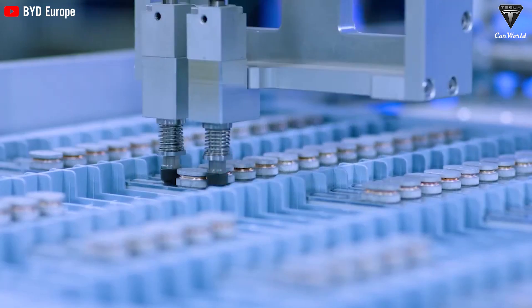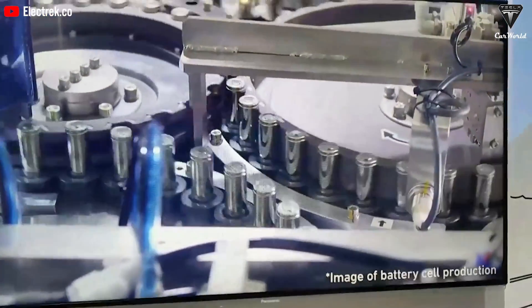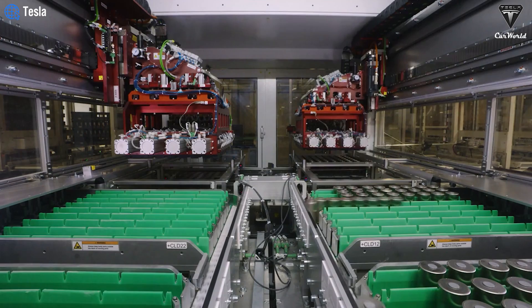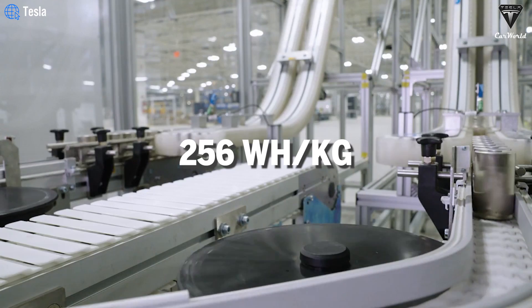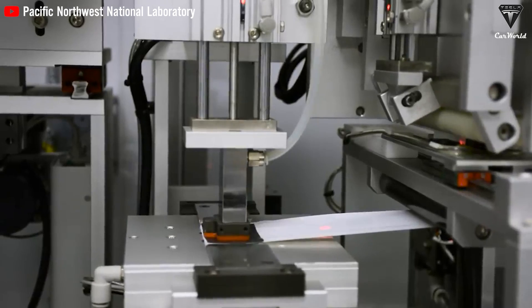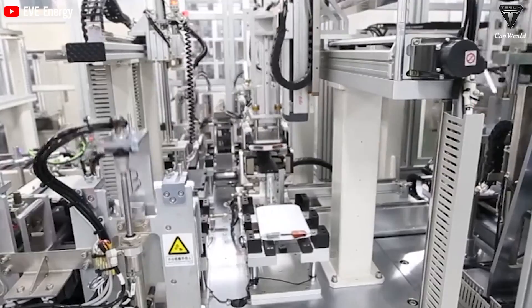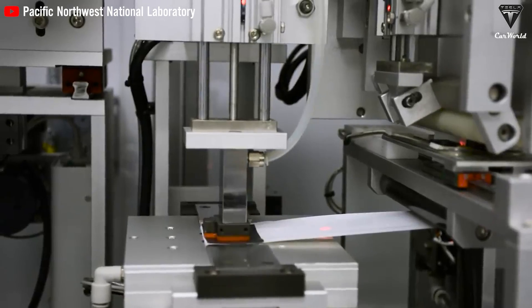When compared to other battery technologies, this battery has 192Wh/kg, lower than nickel-based batteries. For example, the 2170 battery made by Panasonic found in the Model Y has an energy density of 263Wh/kg, and Tesla's 4680 Cybercell has an estimated energy density of 256Wh/kg. However, switching to other LFP battery technologies: BYD's Blade battery has a cell-level energy density of about 168–175Wh/kg, and CATL's Prismatic LFP battery used in the Model 3 rear-wheel drive has a cell-level energy density of about 160Wh/kg. Thus, the 192Wh/kg energy density of Geely's LFP battery is quite impressive compared to competing products.